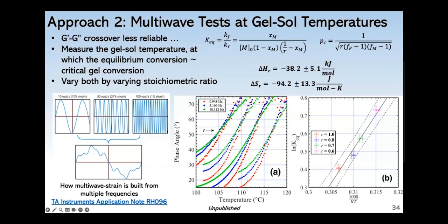So with that testing method, my idea was this. It's easy to prepare samples with various ratios of starting reagent. And if you change that ratio, you can change the critical gelation conversion. And at some high temperature, the equilibrium conversion will be that gel conversion. So I ran multiple temperature ramp tests, shown here in plot A, using the multi-waveform technique. And you can roughly see where the frequency curves become frequency independent by following along this line.